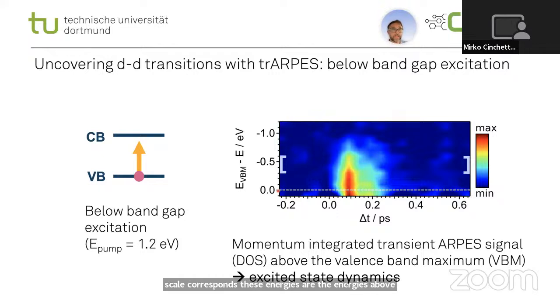So without optical excitation, we would have no intensity above the valence band. But here we see intensity, which means that this intensity comes from the excitation. And what we see here is a kind of density of states of the transient population of the states as a function of time for the different states above the valence band maximum. So we are here sensitive to the excited state dynamics.